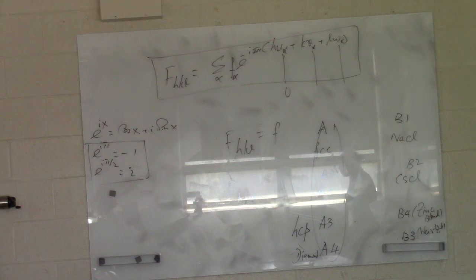Yeah, this is what I want to talk about here. If I put this in summary: simple cubic, any HKL is allowed, right? Because you get just F. If it is BCC, the sum should be even. FCC, either all even or all odd. Sodium chloride, all even or all odd is fine.